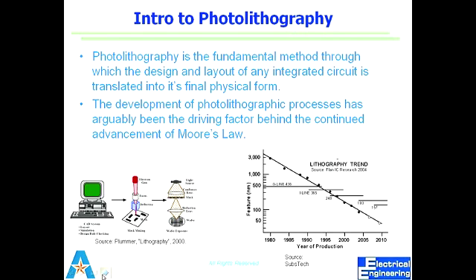again, overall, we use CAD systems to design layout, we simulate our circuit, we check that it fits all the design rules, because on computer it will work, but now once you transfer it into multi-layer masks, we have to make sure that we get all the features down on the wafer, doing the actual processes. And once we get that, we define set of masks from that, which are directly written, because mask is that which contains the opaque and transparent regions, which will be ultimately used to shine on the surface of the wafer in resist, right? So they can have very fine dimensions in there of the features that we ultimately want to make. And then we expose our wafer.